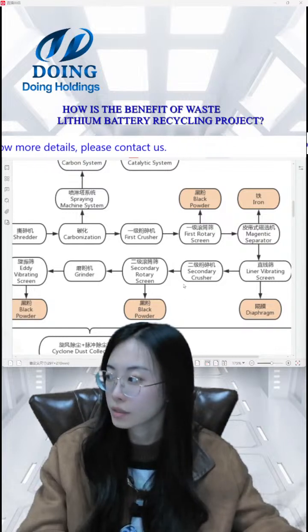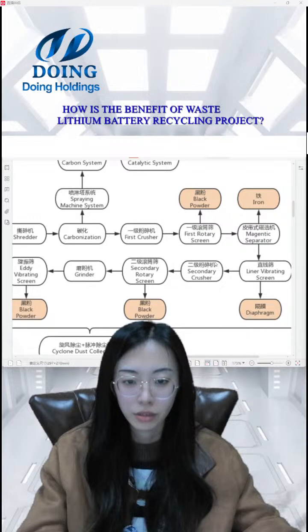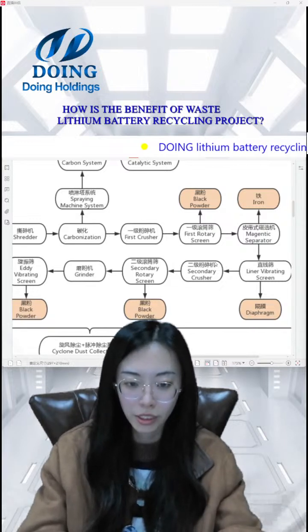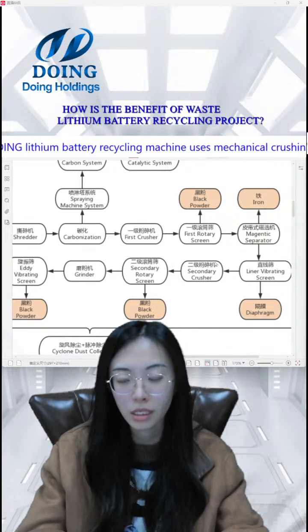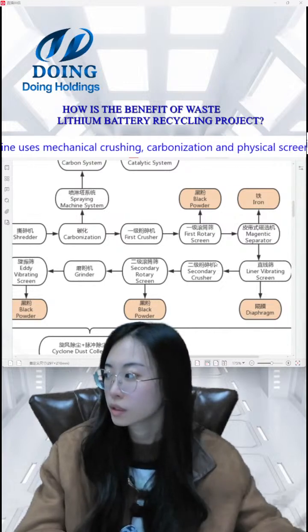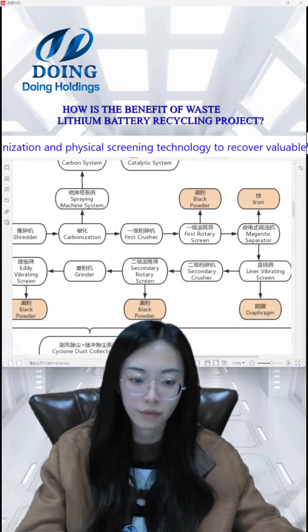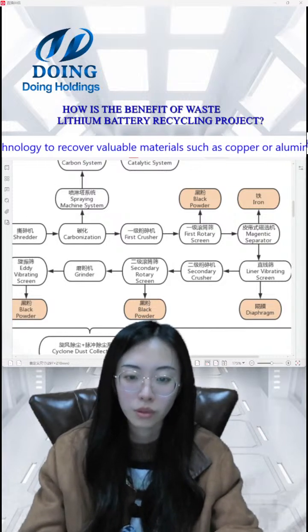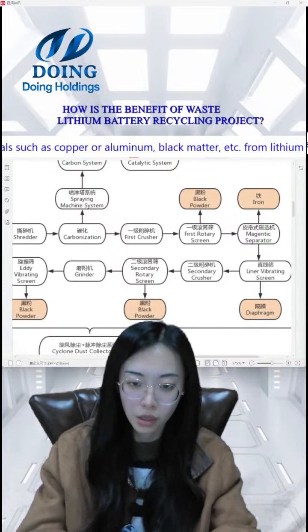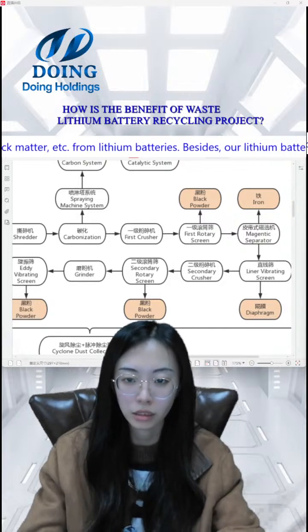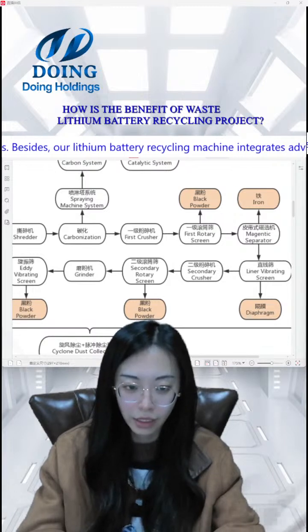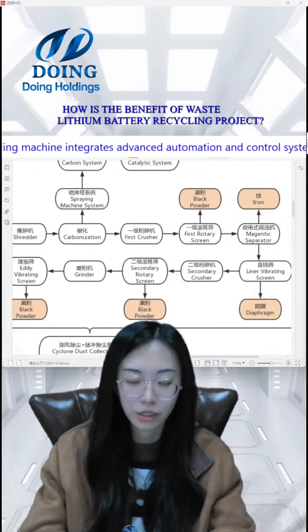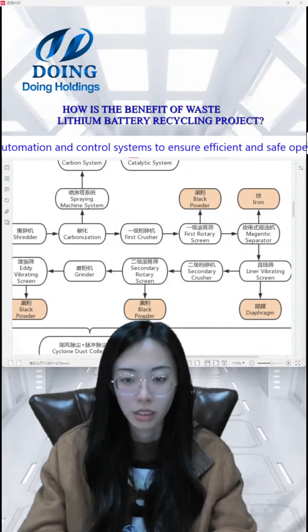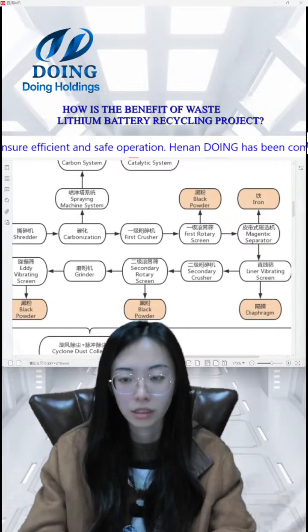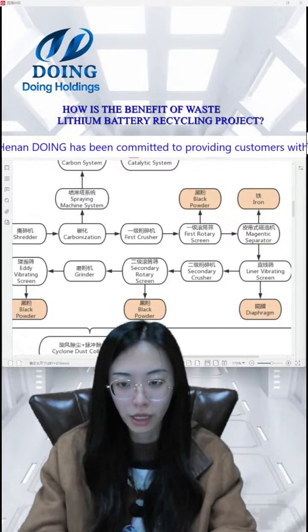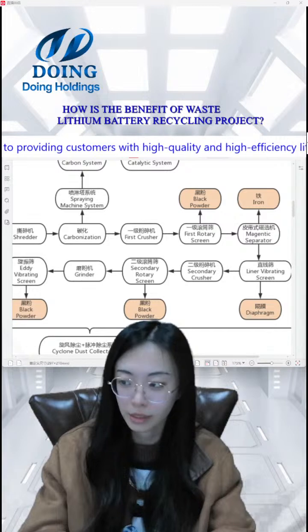And then they will come to the secondary crusher. This is also a hammer blade crusher, with high speed rotation of the hammer blade to crush the material under 6 mm. Then they come to the secondary rotary screen. Also, this is a separation device to feed into a fully sealed rotary screen. The material is all sealed, and inside there is a screen of 120 mesh to the surface rolling rotary screen, and they will just discharge the carbon black that reaches the standard. Then in this step, the recovery rate of the black powder is 95%.